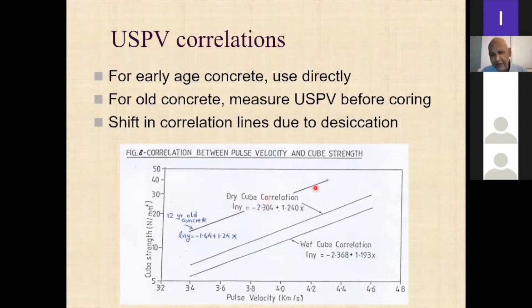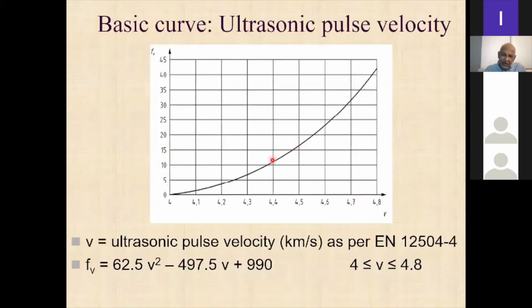And then you can get the optimum value of the intercept by doing a sum of squares or whatever. So what I am trying to say is now actually the Eurocode gives you better guidance. It tells you for each of these correlation points to find the difference from this line. Then you get the mean of the line actually a bit lower than that. I cannot entertain questions on these very detailed things, but hopefully things will get clearer when I do some examples. So like I said, this is the basic curve. When you get these correlation lines, you cannot move away from the shape of the basic curve. That is the main story here.